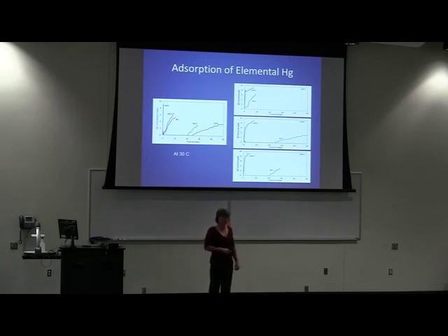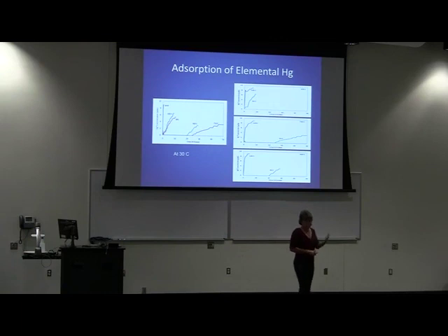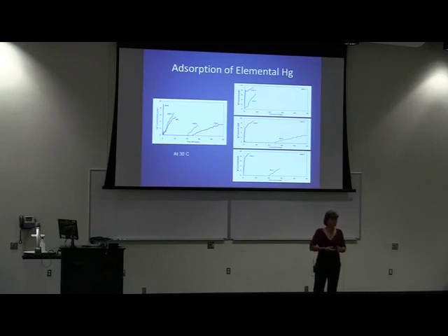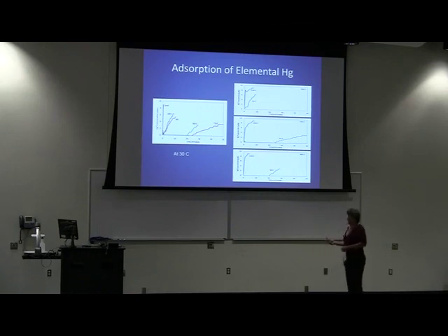If I had done my literature review better, I would have known that this result would have happened. In dry nitrogen, which is what this was in, carbon doesn't have much of an absorption capacity for mercury at all. What happens in the flue gas is that coal also contains sulfur and chlorine. And it's the sulfur and chlorine that attach to the carbon and form sites that oxidize the mercury. And so when mercury is captured, it's captured as oxidized mercury. That's what I learned from the literature search after I did the research. So, in a nutshell, if I was to expand this research, I would look at the absorption capacity of these carbons under different atmospheres with acid gases in them, and also water vapor.